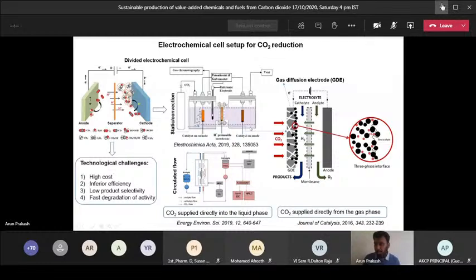So similarly, in your electrolyte, the saturated CO2 from the bulk will move towards your electrode, that is from higher concentration to lower concentration. So because of the difference in the concentration, a concentration gradient will develop near your electrode surface, and this contributes to the diffusion layer, that is 40 to 200 micron thickness. And this migration layer will be only about 0.5 to 5 nanometer thickness. And depending on this diffusion layer and migration layer, this entire process of CO2 reduction may vary.